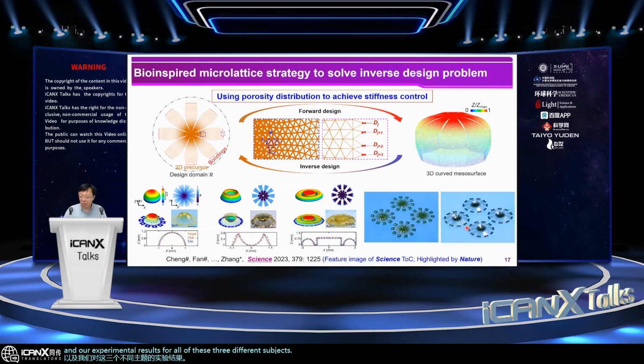And at the right bottom shows the dynamic formation process for the four hemispheres and the volcano-like surfaces. And here I would like to emphasize that all of these mesosurfaces have a curvature radius of only 1 millimeter or even smaller. And previously, it's very difficult to program the curved surface accurately for single crystal structures.